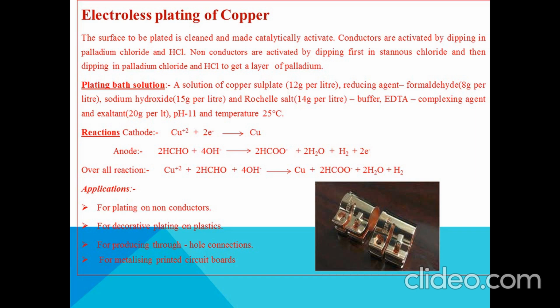After making the surface of the substrate catalytically active, it is then dipped in the plating bath. The plating bath composition is like this. It contains a solution of copper sulfate, that is 12 gram per liter, which provides copper ions during the plating process. Then it contains formaldehyde, which is a reducing agent, 8 gram per liter. Then the plating bath also contains a mixture of sodium hydroxide 15 gram per liter and Rochelle salt 14 gram per liter. So the mixture of sodium hydroxide and Rochelle salt acts as a buffer in order to maintain constant pH.